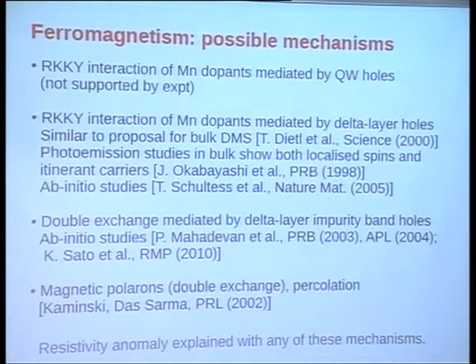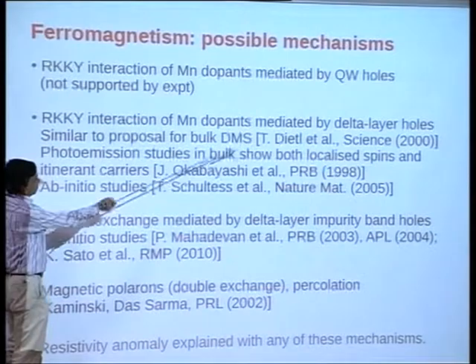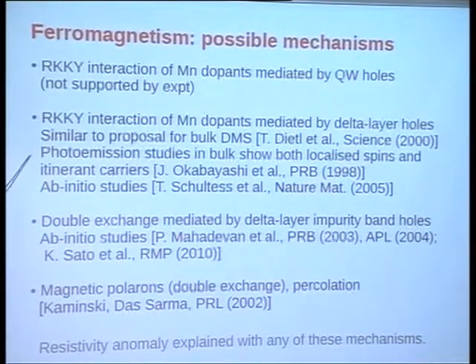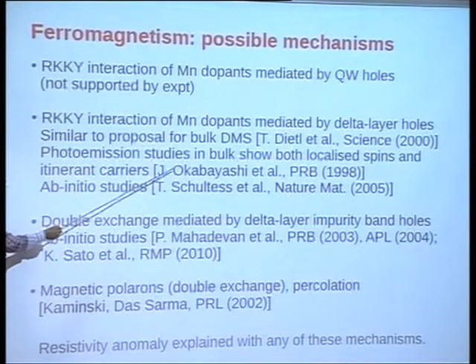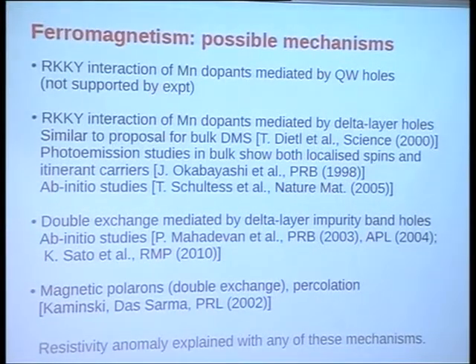But this is not supported by experiment, and so we look for interactions within the Mn layer, which is then going to be a bit like bulk, which brings us to the question whether it is due to an RKKY interaction of the Mn atoms mediated by holes here. This will be similar to the proposal for bulk DMSs by Dietl, and it has been supported by a number of photoemission studies in bulk which show both localized spins and itinerant carriers, and finally at least one ab initio study I know of.